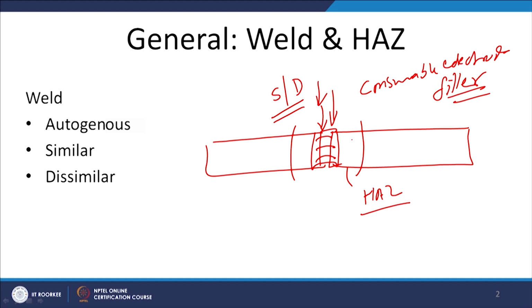The width of the heat affected zone certainly can be reduced. So, from the weldability point of view, we have the luxury, at least in the welding of thick plates, where we can use the filler or the electrode of one or other composition in order to adjust the properties of the weld metal.